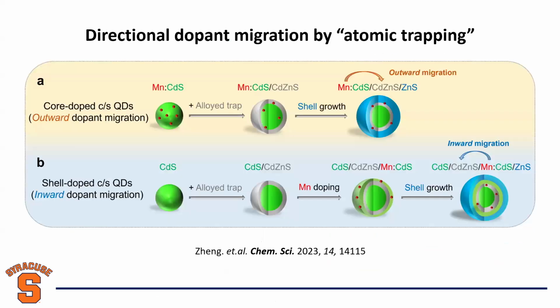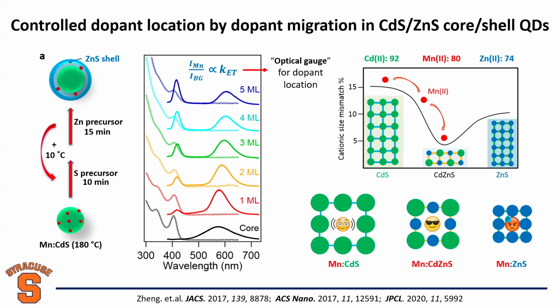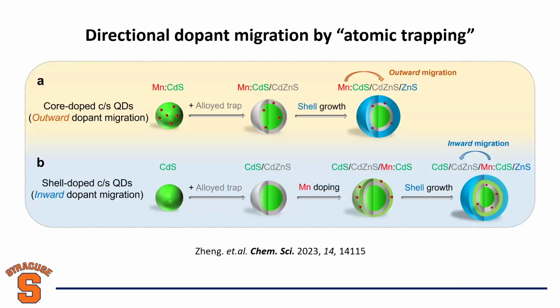Okay, so with many follow-up works, we proved this migration is not the same as random diffusion, and not a direct injection. We're not talking about that work now. Since we proved this is true, and we worked really hard to prove it because some people didn't believe it, we thought that if it is true, we can achieve not just outward migration, but also inward migration. We can use the alloy shell as a target trap for dopants. This is our original work.